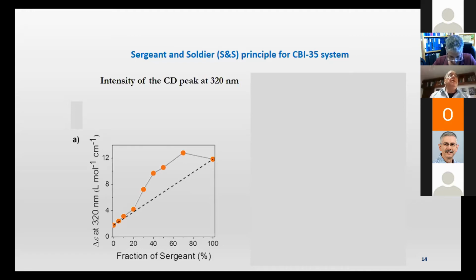And you can measure it by using a CD spectrum, namely measuring the optical activity of the molecule. And here you see the measurement of optical activity when you change the fraction of chiral molecules within the achiral molecules. In the beginning, when you introduce more and more chiral molecules, things are linear, but then there is amplification, and the chirality is induced by the chiral molecules on the achiral ones, and we get very high chirality, even though only 60% or so of the molecules are chiral.